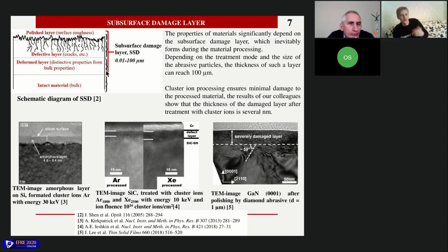Cluster ion beams ensure minimal damage to the processed material, and the results of our colleagues show that the thickness of the damaged layer after treatment with cluster ions is several nanometers.